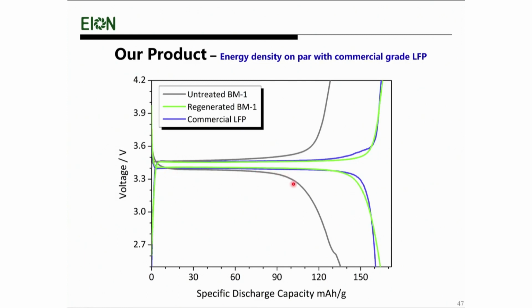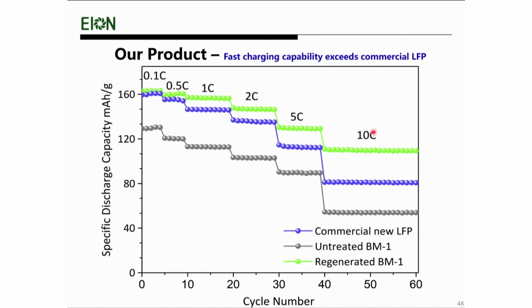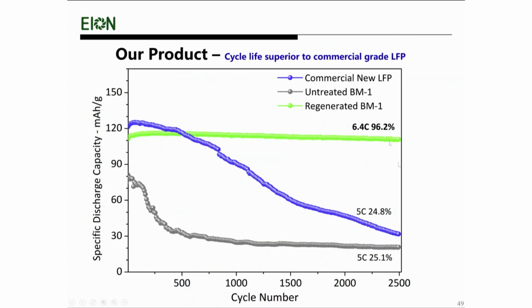So this curve is the voltage capacity curve of the untreated black mass. The green curve is after our regeneration, after we put in lithium, about 20% lithium back. And the blue curve is the commercial, completely new lithium iron phosphate. So we are actually able to achieve similar capacity. And indeed, because of the recrystallized sub-10 nanometer grains, we're able to achieve at high rate even better performance and pretty good cycle life at these very high rates.